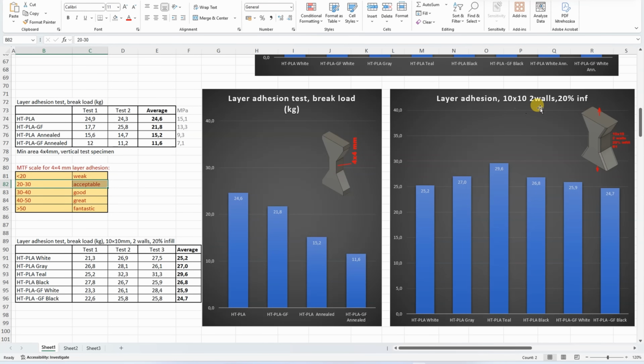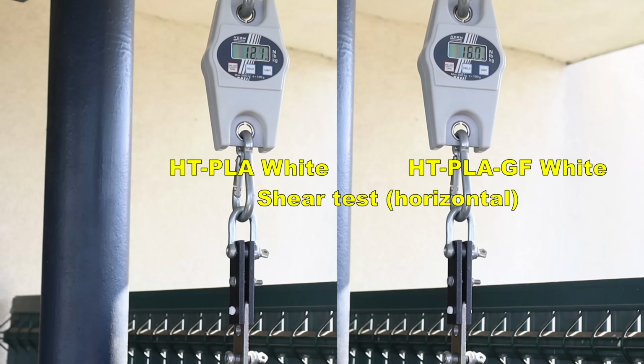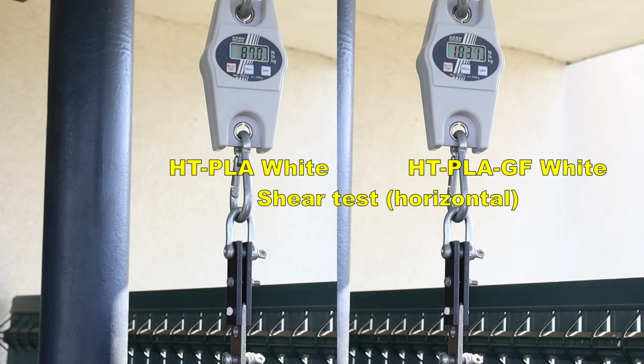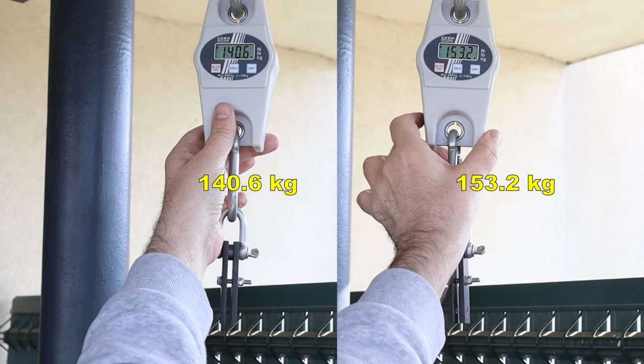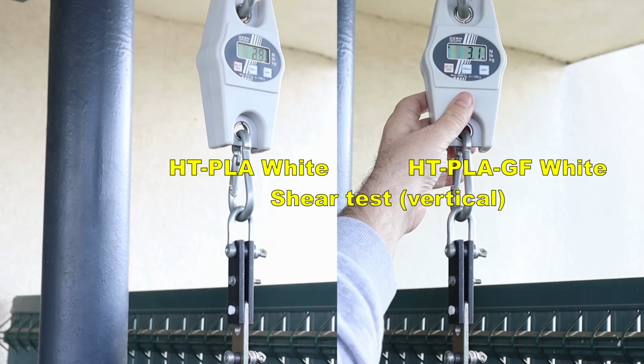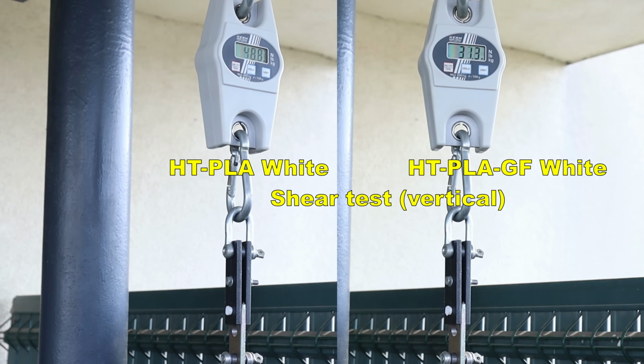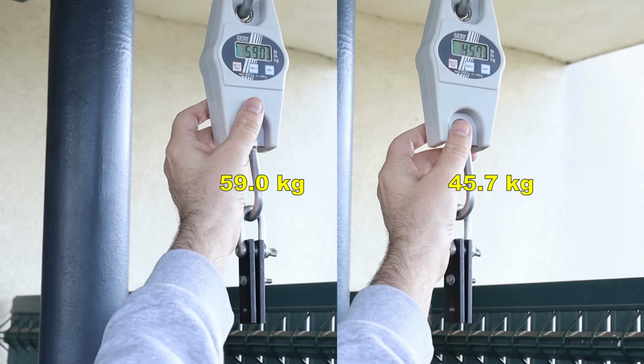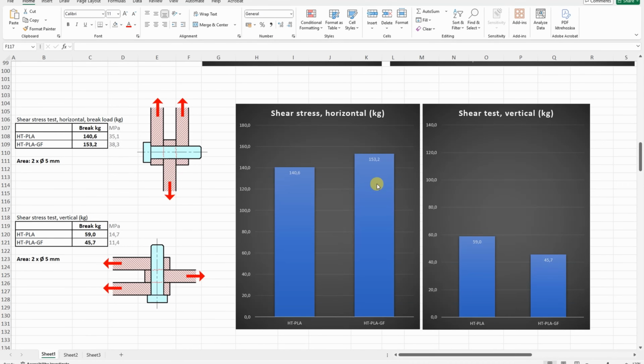With this 10x10 with 2 walls and 20% gyroid infill, we can see more or less similar values. Here we can see some smaller peak, but what I'm happy about is that the glass fiber version is not weaker compared to the regular HT-PLA. Shear test with horizontally printed objects, and usually glass fibers help here, and now vertically printed, and in this position usually glass fibers reduce the strength. Exactly as expected, but the difference is not big. And actually in all 4 cases, these are good values.